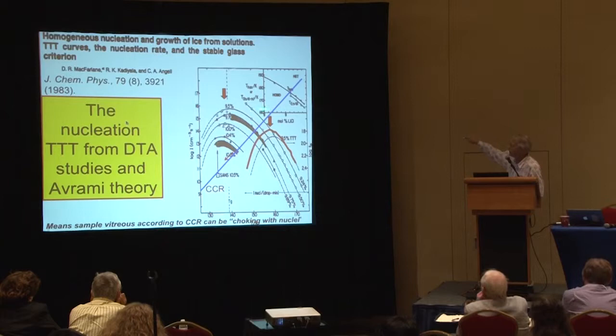So if you follow a critical cooling rate which bypasses the nose, and you say, aha, we've done it, actually what you've done is to plunge your system into the nucleation zone. So your glasses that you formed are choking with nuclei, if you like. And all you have to do is to heat it up again, those nuclei will grow, and whatever you were trying to protect is no longer protected. So